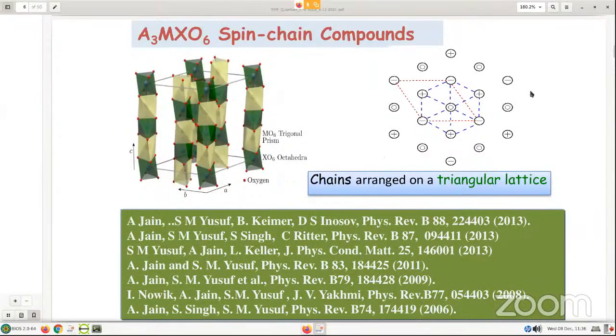We have also worked on a 1-dimensional spin chain kind of system, where these magnetic atoms form a triangular lattice. That means here you see the magnetic atoms are along the c-axis, but when you see in the AB plane, they form a triangular lattice. We have also worked on this. So I'm trying to tell you that crystallographically, though we have dealt with a 3D system, as far as the magnetic lattice is concerned, it can have really lower dimension. So not necessarily do you have to make an artificial low dimensional magnetic lattice all the time. Even in a 3-dimensional system, you can look for it. And we have worked on this kind of system.